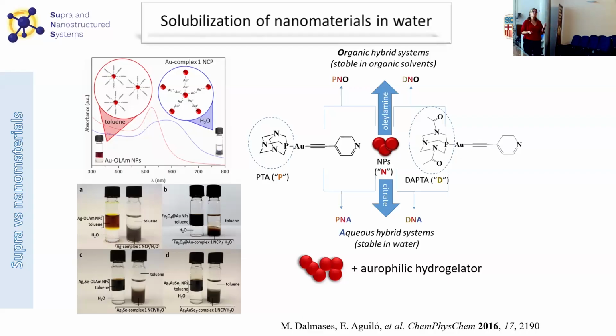So this worked whenever our nanomaterials have metal centers that can induce metal-metal interactions with our hydrogelator. So this was useful with gold nanoparticles, with silver nanoparticles, with a mixture of different nanoparticles having gold or silver at the surface. But for example, it doesn't work with iron oxide nanoparticles. But if we make a thin film of gold at the surface of the iron oxide nanoparticles, then the process works. So we need a gold center or a metal at the surface that can establish these metallophilic interactions, and then we can induce a fast solubilization in water of our samples.